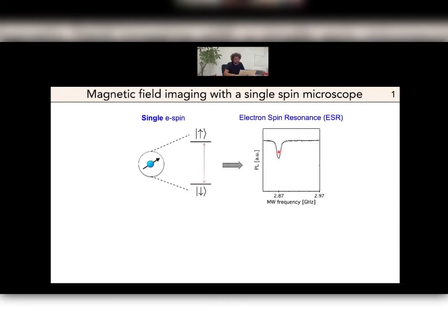If now a magnetic field is applied, then owing to the Zeeman shift, there is a splitting of the electron spin sublevels, and as a result, a shift of the electron spin resonance frequency. And what is interesting here is that the Zeeman shift is directly proportional to the magnetic field at the location of the single atom. So you have somehow a quantitative measurement of the magnetic field within a detection volume that is given by the